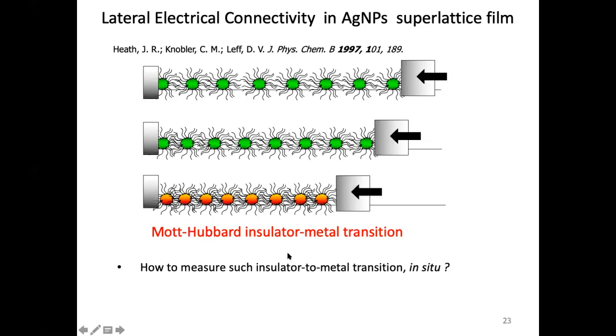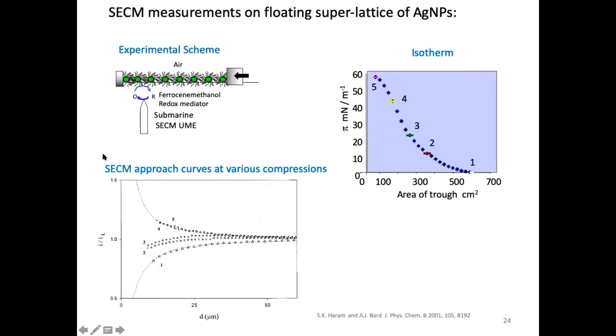Well, this is again an indirect measurement. What we have done is exploit this SECM facility, or SECM technique, to measure this change in conductivity. I think you already remember that if my film is conducting, I'm going to get positive feedback. If the film is insulating, I'm going to get negative feedback. Let us see what happens. This is a film in this Langmuir-Blodgett trough. The nanoparticles are floating at the liquid-air interface, and this is a kind of isotherm. A normal isotherm in thermodynamics measures pressure versus volume; here I'm measuring pressure versus area.